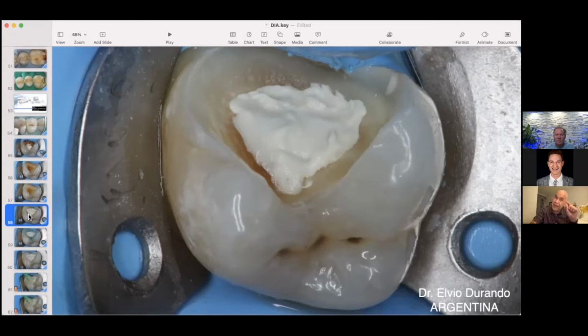But if you put too thick of a layer, when you cure it, it's going to flake away. Why? Because it didn't cure in the bottom. So yes, if it's too thick of a layer of any of these liners, you're going to have cohesive failure. That's why you need to be really careful. If you're going to be a lining guy, lining has to always be less than 1 millimeter, whatever material you're going to use. A liner is defined as something you put on dentin that is less than 1 millimeter. If it's more than 1 millimeter, it's not a liner anymore, it's a base. And that's a different story.